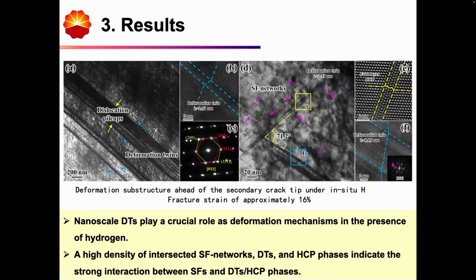Second, if we enlarge the localized observation regions, we can see some very complicated interactions. First, it has some stacking fault networks. In terms of the HELP mode, it will promote stacking fault planar slip along different 111 slip planes, which causes some cross sections.